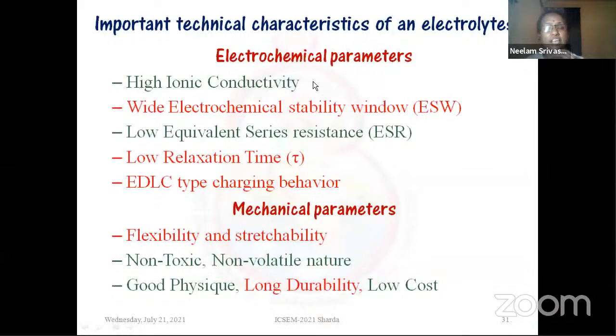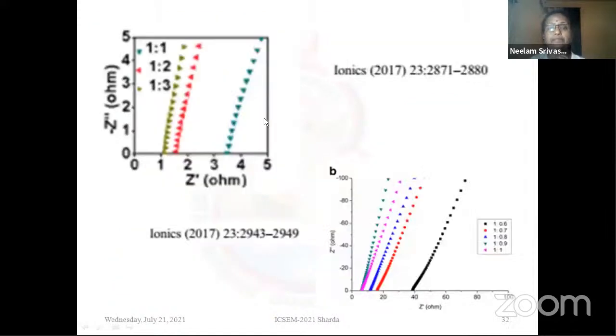So all these systems which we have studied, and which we see from the application point of view, we need high ionic conductivity, wide electrochemical stability, low ESR, meaning equivalent series resistance, and low relaxation time. We need EDLC type of charging discharging behavior, because my concentration is more on the supercapacitor. So EDLC type of charging behavior is required for my system. And mechanically, naturally, you need flexibility, stretchability, non-toxic, non-volatile nature, good physique, long durability, low cost. All these have been achieved, and for this we will see in the coming data.